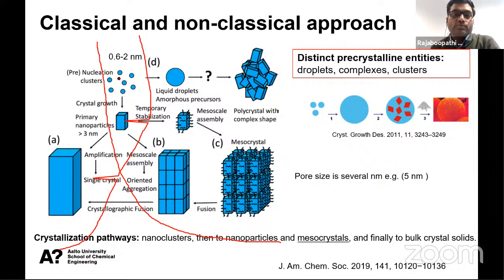What is non-classical growth? So this is the nucleation cluster. Also, there may be a pre-nucleation cluster. We saw it is a dense liquid phase. It is not only the dense liquid phase in the pre-nucleation cluster, there may be different things. For example, sometimes it may be droplets, sometimes complexes, sometimes small clusters. So after the pre-nucleation cluster, it will reach the nucleation cluster. Once you have the nucleation cluster, you can get the nucleus. The nucleus will attach here in a crystallographic manner to produce a mesocrystal.